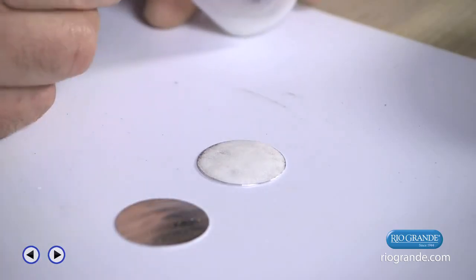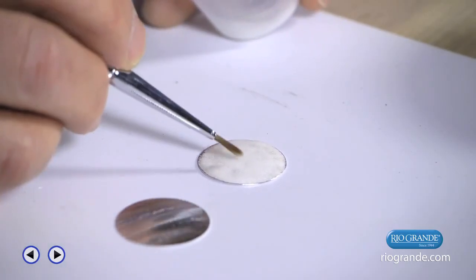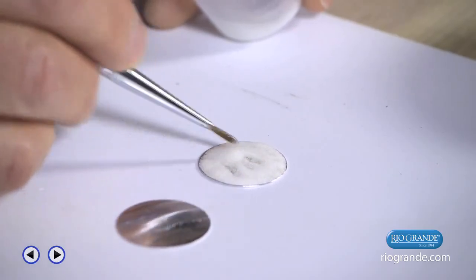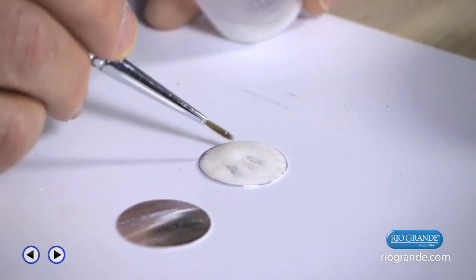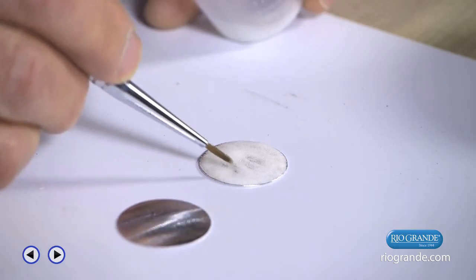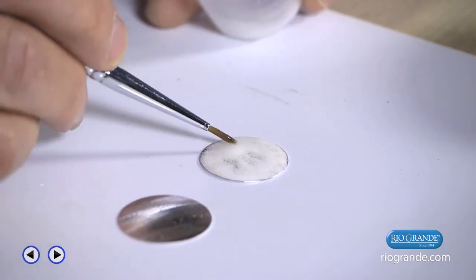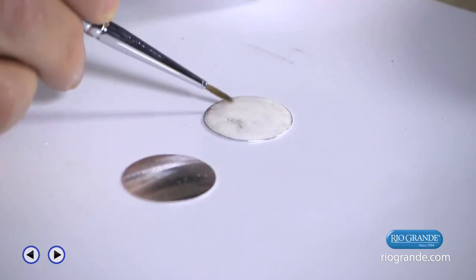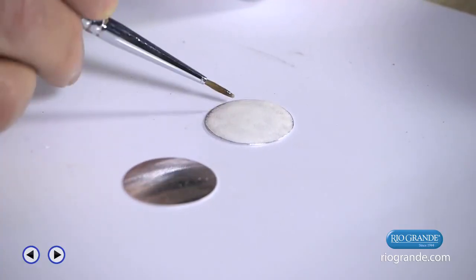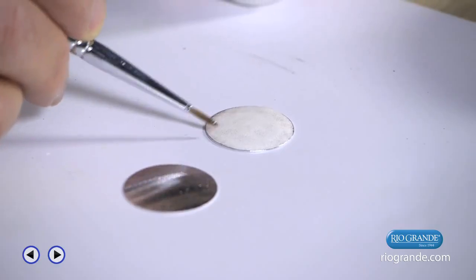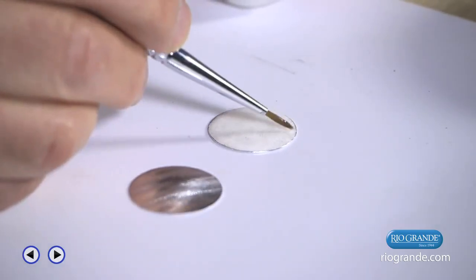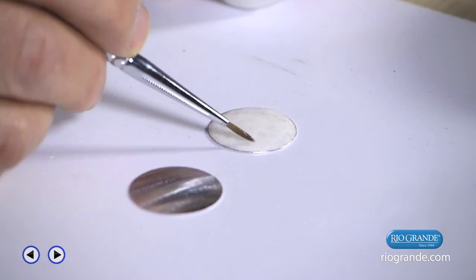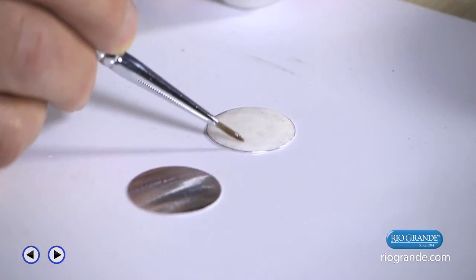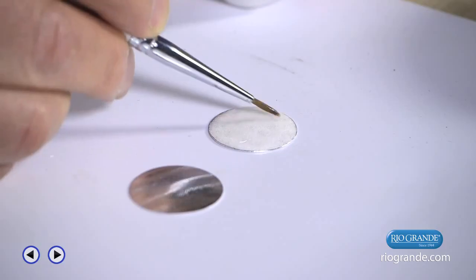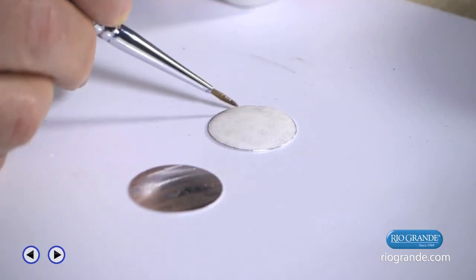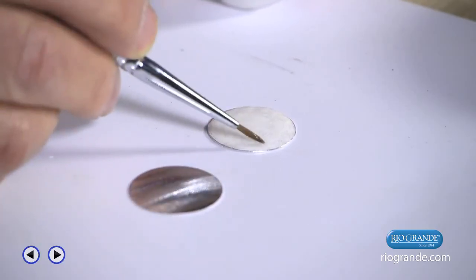And what I'm looking for is it not to look white. So when it looks, I'm going to pull some over here. When I'm not seeing the silver color through, it's too thick. And where I'm seeing the silver almost bare, it's too thin. So what I'm trying to do is move the enamel, and I'm using just the tip of my brush with a very, very delicate touch. And I'm touching the highs so they flow into the lows, sort of like pushing the mountains into the valleys. Moving it out to the edge as close as I can get it without running over the edge.